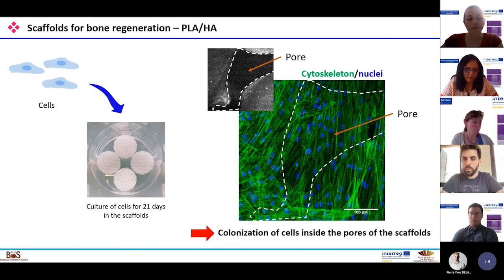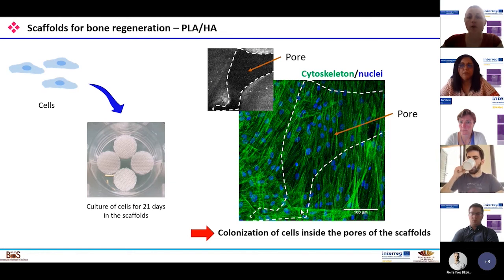These results suggest that we have more and more cells in the scaffold over time, and then we checked this suggestion by labeling the cells after the 21 days of culture. So you can see on this picture, we have the nuclei of the cells in blue and the cytoskeleton in green. And you can see that we have a lot of cells that are aligned and elongated on the fibers of the scaffold. But also, here you have the pore which is represented, and we have also cells inside the pores of the scaffold.